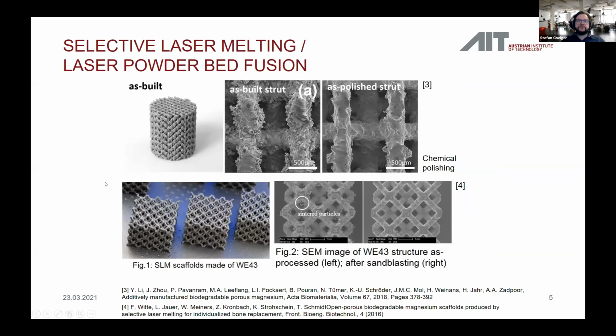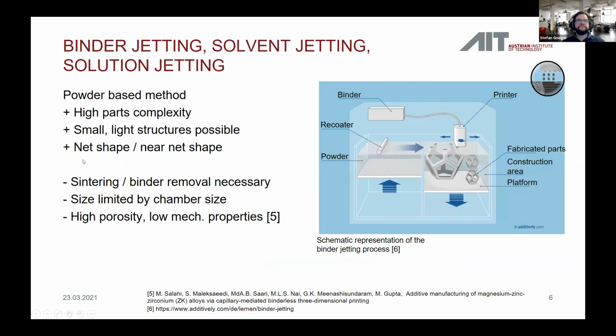So here are 2 examples for magnesium parts produced via selective laser melting. We have already seen some, so here are 2 more. As you can see, these are small parts with a very high complexity, with hollow areas, and very, very small features. These bridges have a width of lower than 500 microns. As you can see, with post-processing, you can even increase the surface quality of the parts. So small, lightweight, highly complex parts.